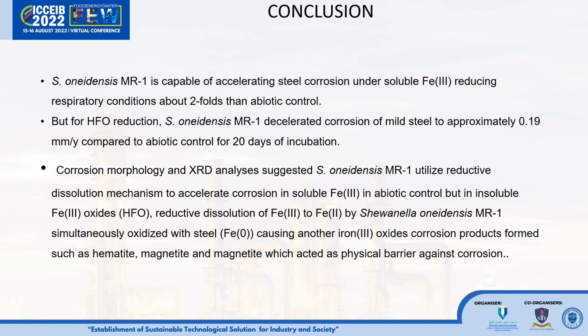Okay, in conclusion, the reductive dissolution process was highly influenced by both the solubility of iron 3 compounds and the presence and absence of iron-reducing bacteria, IRB. Shewanella oneidensis MR-1 is capable of accelerating steel corrosion under soluble iron 3 reducing respiratory conditions about twofold compared to the abiotic control. But for HFO reduction, Shewanella decelerated corrosion of mild steel to approximately 0.19 mm per year compared to the abiotic control.